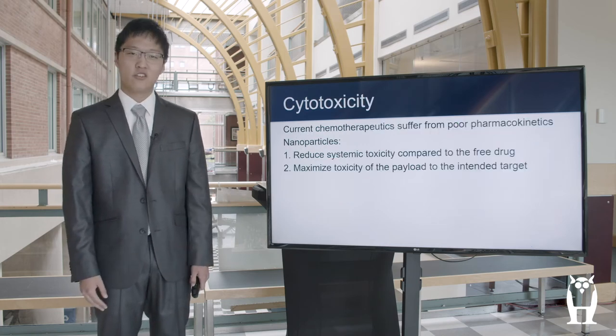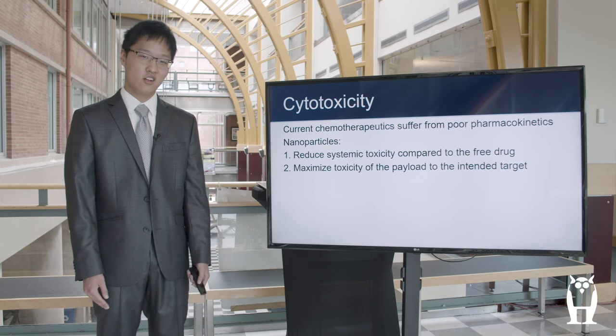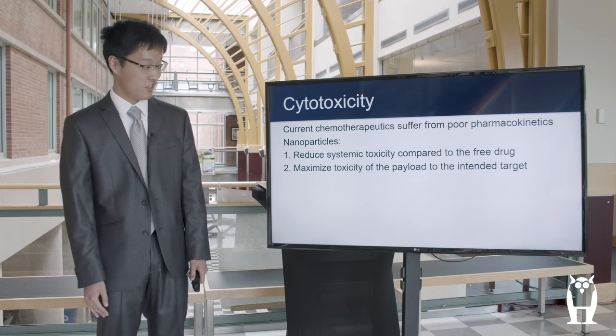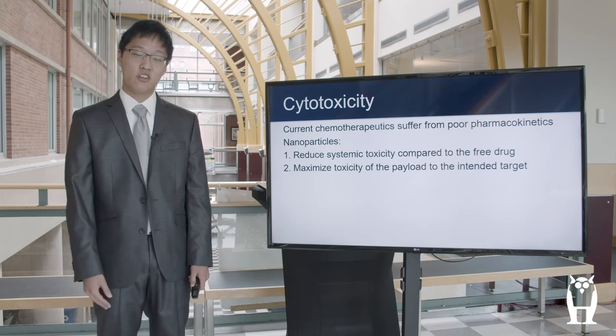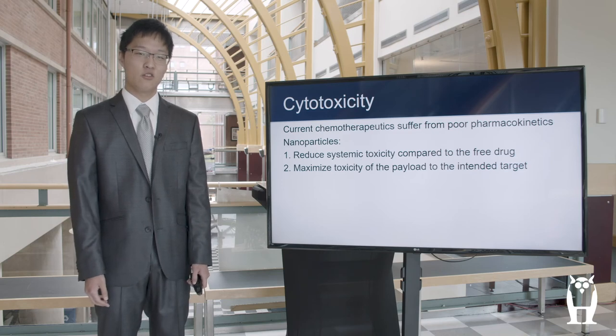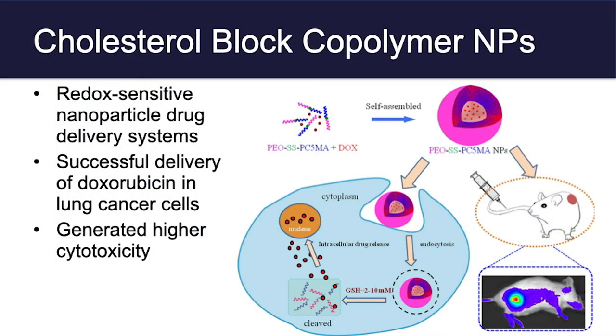Finally, we have the issue of cytotoxicity. Our third challenge involves current chemotherapy treatments that suffer from nonspecific and systemic toxicity. Nanoparticles solve this issue by reducing systemic toxicity and also increasing toxicity to the cells that we want them to target. In this study, these cholesterol block copolymer nanoparticles allow the release of doxorubicin after the nanoparticles enter the cell. They were found to be more toxic than other variants of nanoparticles and also non-toxic to healthy cells, which is beneficial for ultimately treating cancer.